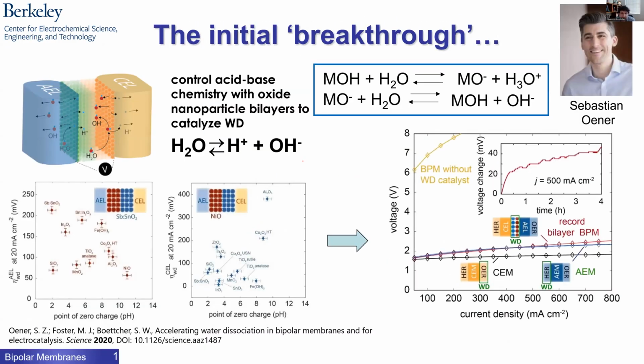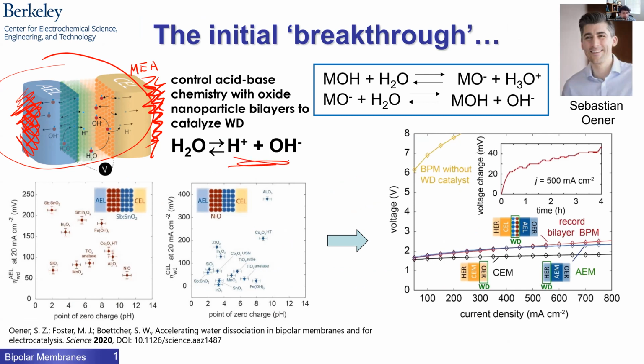Well, there's an early study we did. We really started getting interested in this 6 or 7 years ago now. There's a lot of work to get going here. We did a couple things. We started studying these, really the first to look at these in so-called MEA geometries, membrane electrode assemblies. And what that allowed us to do is there's no other ions. We don't have any contacting salt solutions. We put the electrodes right on, just like a membrane electrolyzer, membrane fuel cell. In fact, we just adapted our expertise in those areas to do this, which was very useful because that means we can study these species transporting and dissociating in the absence of all other convoluting ions that might be present. And then, building off very nice work, I think in the late 80s, by Simons, who